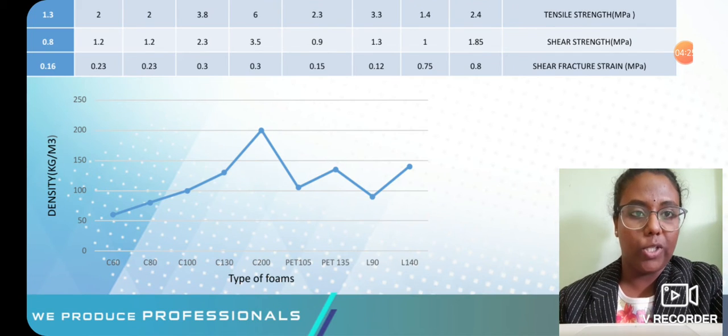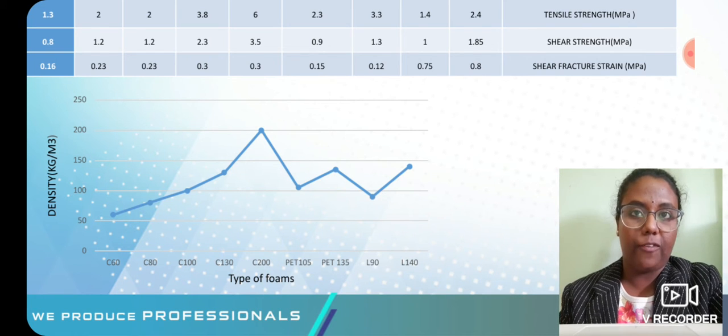And these lines conclude that for plain foams, higher density achieves a failure mode with a high tensile stress under indenters, which gives rise to a low energy mode of fracture. Therefore, the lower density foams fail in a higher energy shear mode, while the high density foams failed as a result of a lower energy combined tensile or shear system.